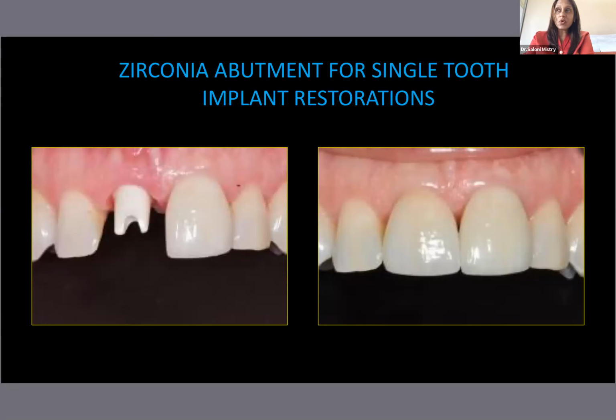Nowadays, we have the tribochemical silica coating, which is done for the Ti base. You have certain conditioning of the Ti base and the zirconia bases, which are done in order to enhance bonding. You have to use a silane coupling agent after the tribochemical is done. I will show you in my next pictures the entire bonding technique, and that's how you then get the desired effect with zirconia based abutments in single tooth implant restorations.